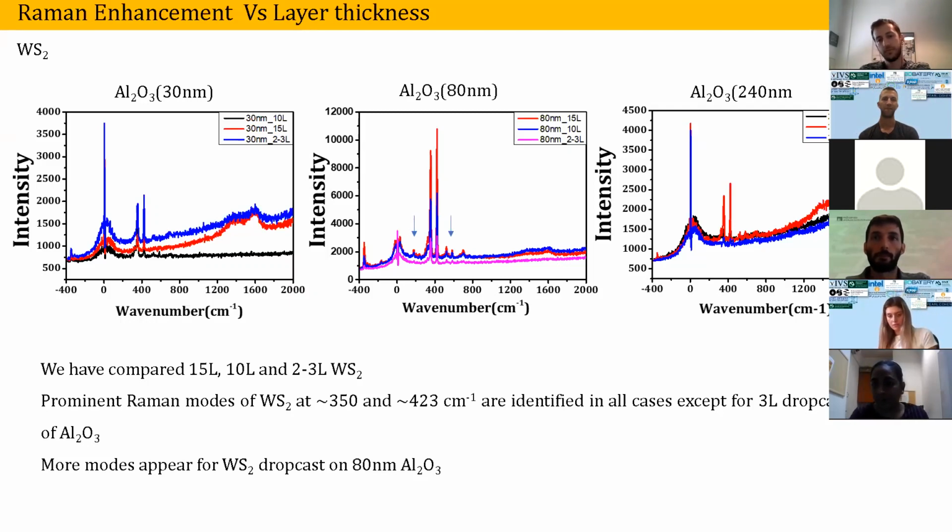It's kind of an interference effect. We have quarter-wavelength interference, lambda by 4, and we have the metal and metal oxide thickness correspondingly chosen. And all the metal is almost the same here, only the alumina layer is changed. So it's kind of an interference effect.